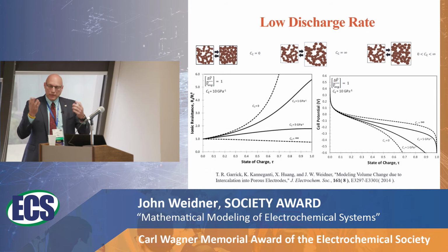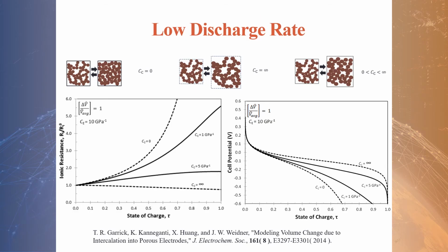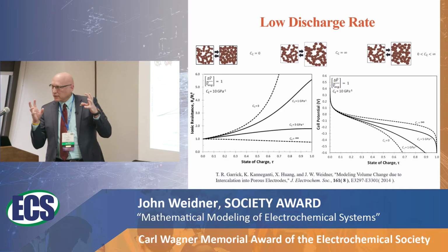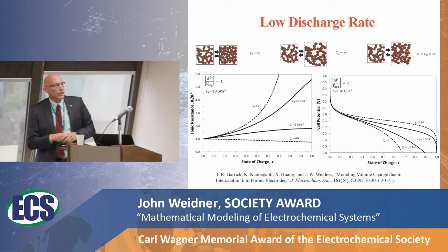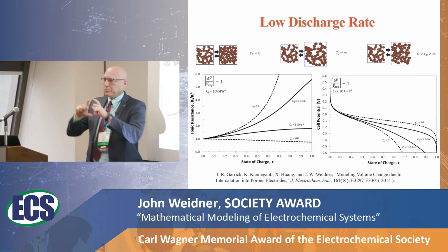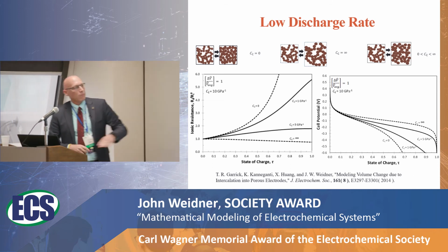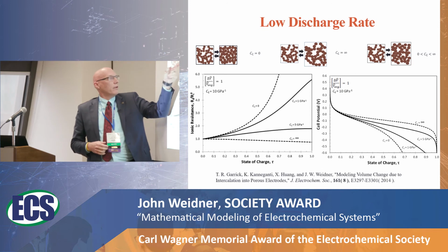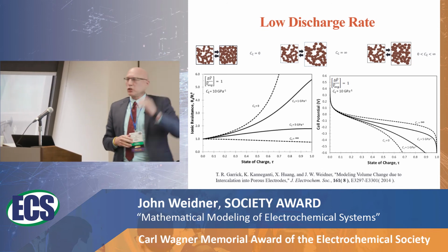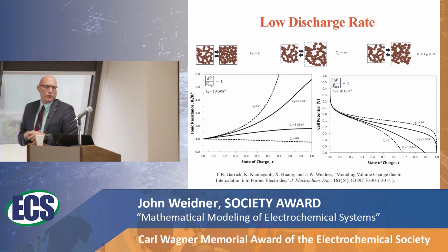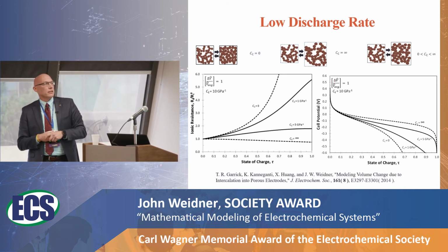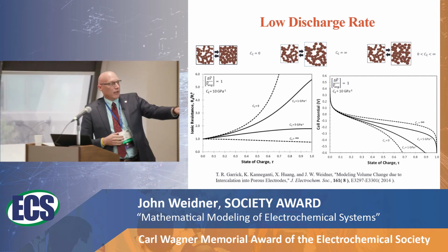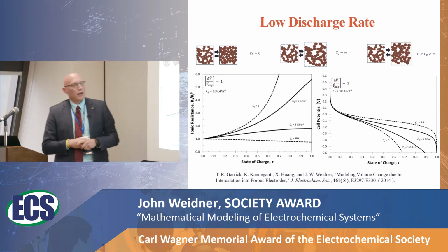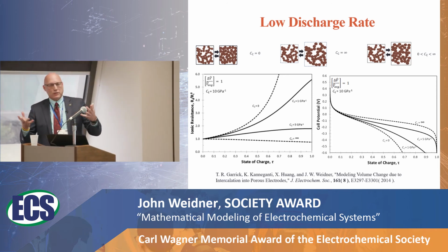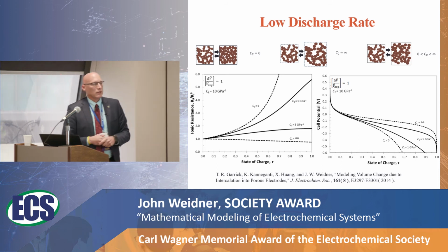And how significant is this? Even when we assumed G was constant, we realized it could be quite significant. If the can doesn't offer any resistance, the one on the right, the ionic resistance, which we can measure by relating it to the porosity, actually drops a little bit, because the cross-sectional area expanded a little bit. But if you force all of it to go into porosity change, the resistance goes up dramatically. The Bruggeman coefficient changes to the 1.5 power, so it's very sensitive to porosity. So where we are on this curve is going to dramatically affect the resistance, in this case the ionic resistance, and in fact the cell potential.